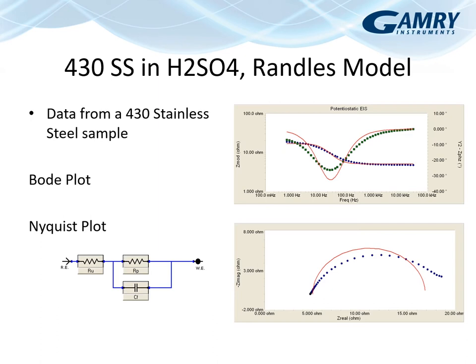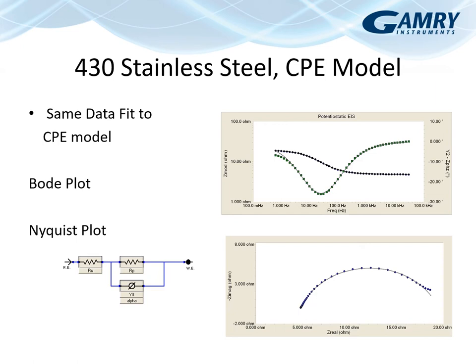What we do — and what you will do with almost any real sample — is substitute that capacitor for a constant phase element (CPE). You can see the dramatic improvement in fit by using a CPE instead of a capacitor. You need to do this for all real systems. Real systems are not ideal capacitors, especially in electrochemistry on the corrosion front or where you've got a double-layer capacitance. Coatings can get close to ideal capacitance, but with an active electrode you will see non-ideality on the capacitive front.